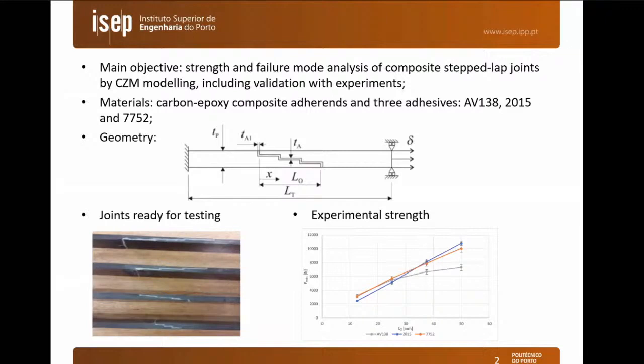The materials of the composite joints are carbon-epoxy composite adherends, and we are testing three different adhesives: two epoxy adhesives, AV138 and 2015, and a polyurethane adhesive, the Sikaforce 7752. The main parameter that we varied in these joints is the overlap length, named LO in the figure. We can see also an example of joints ready for testing in the picture below, namely the side view, in which the three-step configuration and the adhesive joining the two composite adherends are visible.